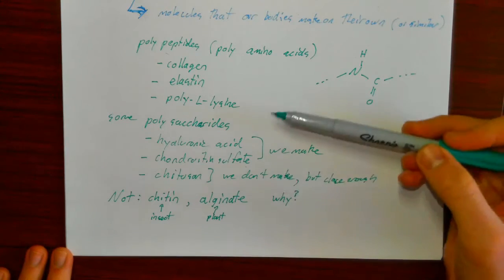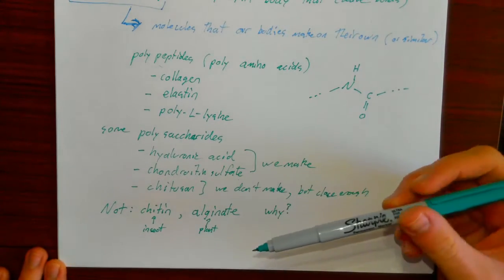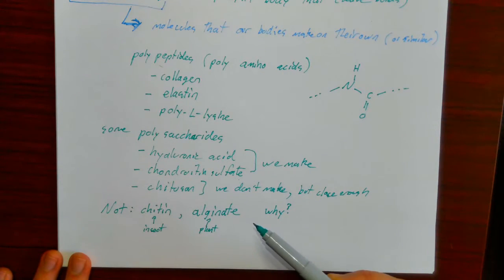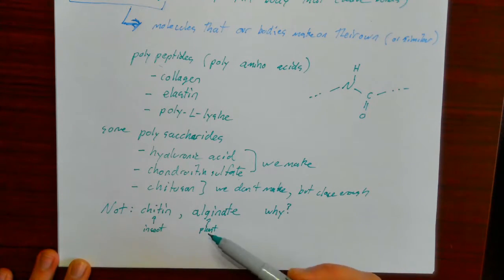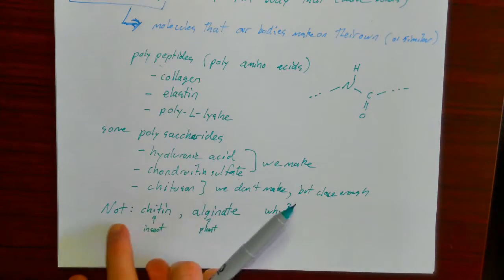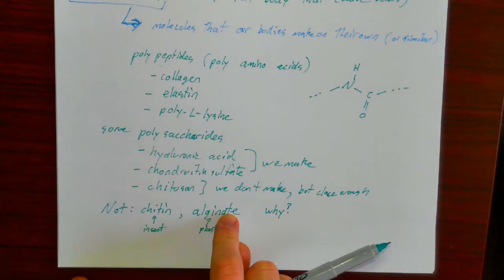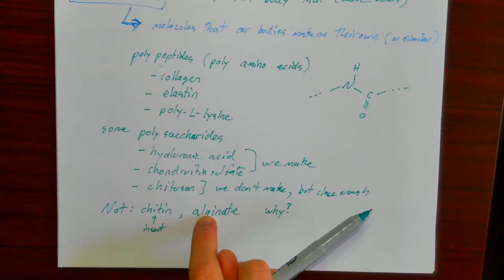So what does it mean? Well, this actually provides some benefit to us in a bioengineering context. For example, my spouse did some tissue engineering projects where she was making artificial intervertebral discs, and she made the jelly-like center of the discs in between your vertebrae out of alginate, such that they would last long enough. Because our bodies don't have enzymes that can break down alginate very quickly, that alginate construct could last long enough to be effectively integrated with the host tissue.